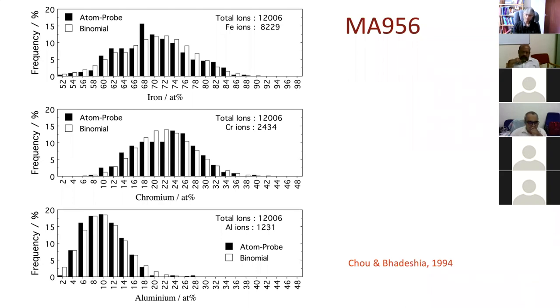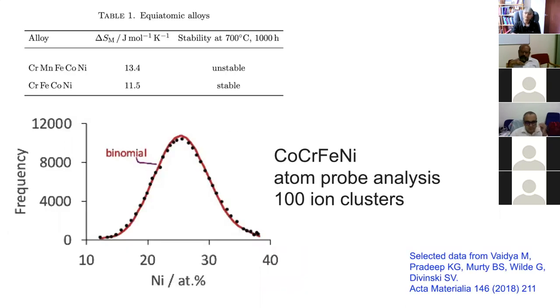And this work has been done in the case of a high-entropy alloy. This is the cobalt, chromium, iron, nickel system. And we're looking at 100 ion clusters in this case. The comparison of the experimental data, which are the black points, against the binomial distribution is really very good for this alloy, which we decided was stable after holding at 700 degrees centigrade for 1,000 hours.